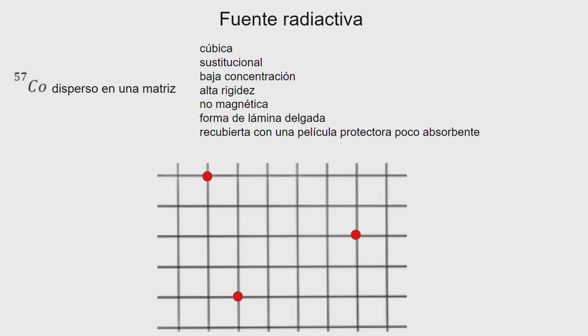But this, as we will see, also it is used because it has no internal intrinsic magnetic field. It's not a magnetic material, so that you don't expect to have a splitting of the lines that are emitting because of a magnetic field. And it has a cubic structure. So if you have rhodium, which is very pure, and you have your Mössbauer probe substitutionally in that lattice, then there will be no electric field gradient, and you will not have a quadrupole splitting.